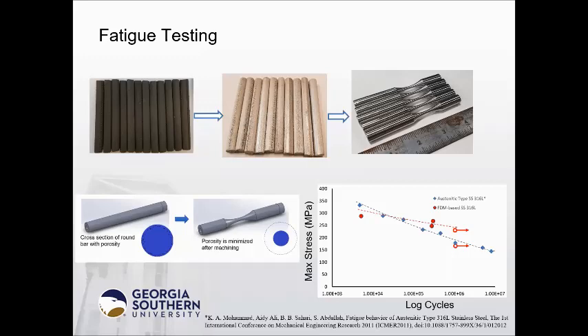I assume this is attributed to the defect inclusion of the flat bar. But when we machine the fatigue bars, those cross sections have less porosity underneath the subsurface, so it has a lot higher stress for the failure. This indicates that the round bar after machining may have a higher tensile strength in comparison with a flat bar.